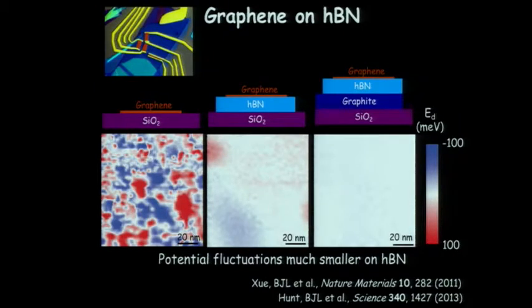Do you know if the graphite for sure helps, or it's more the thickness of the HBN that does? I mean, I would think that thick HBN should work just fine as well. Or in other words, have you done thin, same? So this is thin HBN, relatively thin graphite. So it could be that you use thin HBN and graphite, or you use thick HBN, you get the same